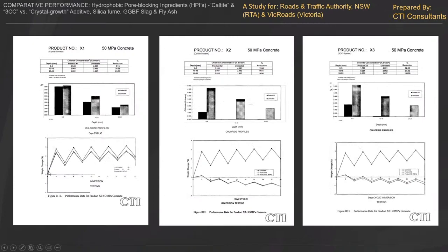What's interesting is if you look at material one, which was the crystal growth product, they ran it through not just a normal absorption, but a series of wetting, drying, wetting, drying, wetting, drying, etc. And if you look, the general trend is that it's getting heavier all the time. It's absorbing more and more water. So eventually that concrete will saturate. If you look at the HPI, on the other hand, the line is going down, so it's wetting, drying, wetting, drying, and the line, you can see, is going down. Also shown here is another HPI, another Cementaid product we call 3CC, which is used at a slightly lower dosage rate and is slightly less expensive, and it's very, very similar.